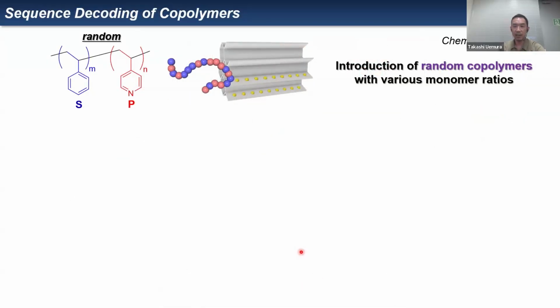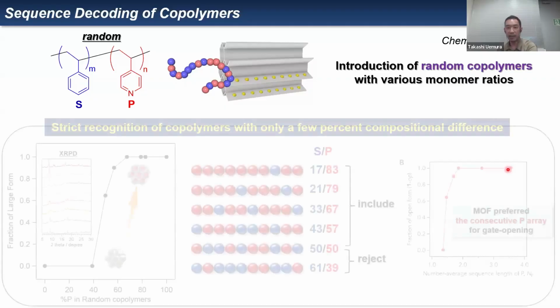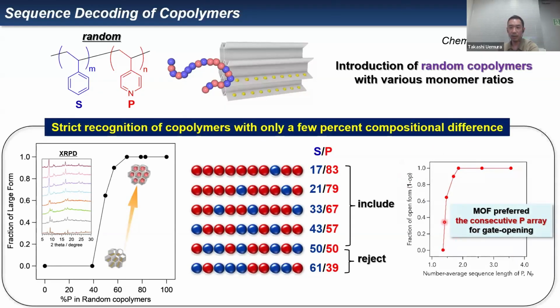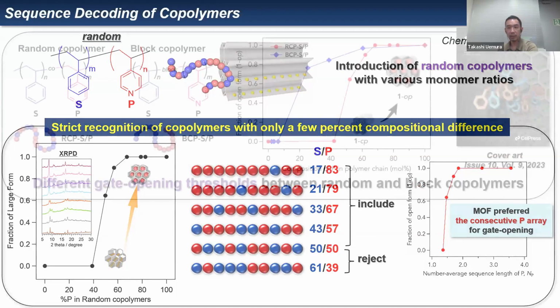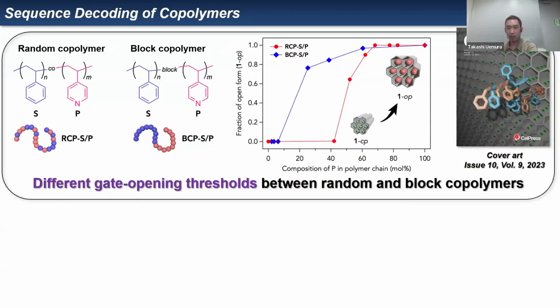The biggest challenge is the sequence decoding of the copolymers. Here we introduce random copolymers with various monomer ratios and found that the MOF preferred consecutive arrays for the gate opening, which can allow the strict recognition of the copolymers with only a few percent composition differences. Then we used block copolymers, which show different gate opening thresholds between random and block copolymers. I mean, these block copolymers are more easily adsorbed.